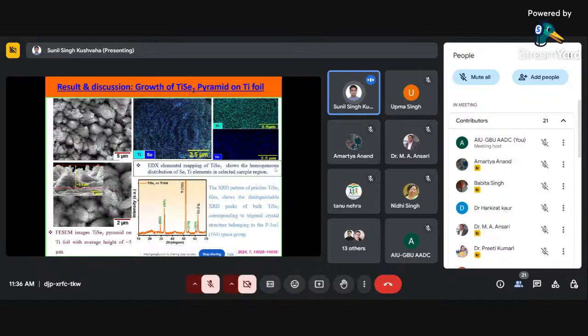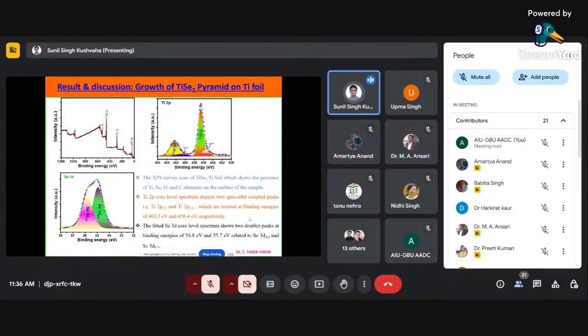So this is simply we heated titanium foil inside the selenium environment at 500 degrees Celsius, and we can clearly see the formation of the pyramid structures. I think we have shown before that if we have only titanium foil, it is a plain surface, not a pyramid surface. And after the elemental mapping, we can clearly see titanium and selenium are there, clearly showing the formation of TiSe2. We have also done XPS measurement, which also shows the formation of TiSe2.